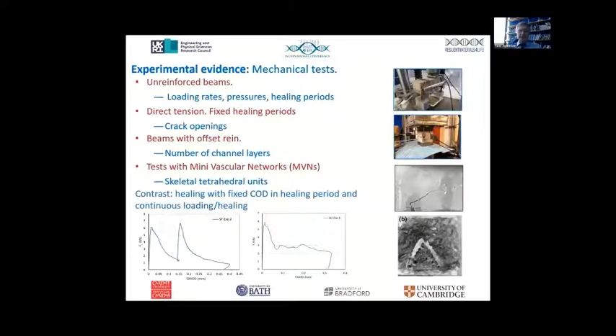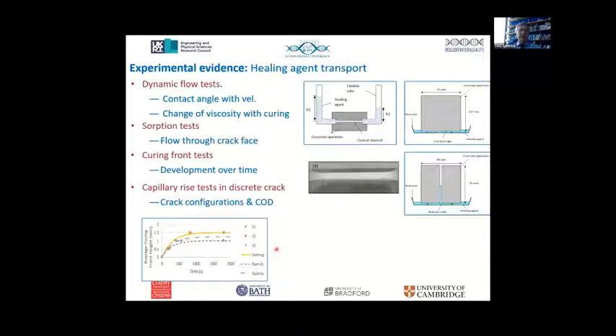I just want to highlight one thing with these two simple graphs. If you look up lots of fairly traditional stuff on self-healing, you will see graphs like the one on the left, where something is cracked, it's allowed to heal, and then it's re-cracked, and the crack is static in the healing period. If the crack is not static in the healing period, you get very different behavior, and this varies greatly with the rate that it's loaded. That's when the healing agent starts to flow into the crack. We got experimental evidence on healing agent transport.